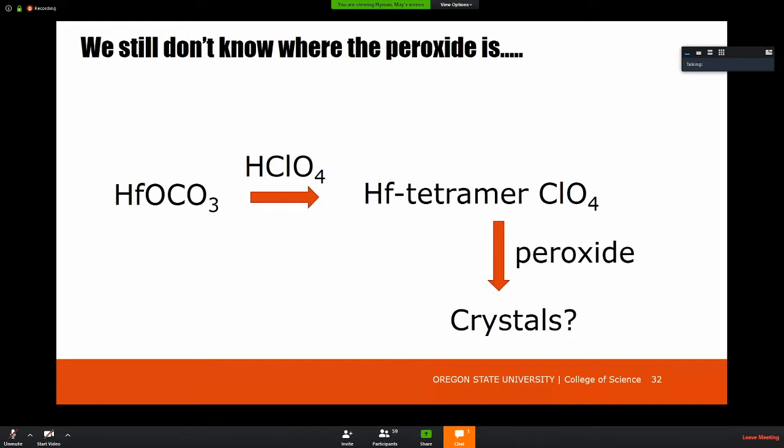Zirconium actually catalyzes decomposition of peroxide and forms oxos. And the oxos link the zirconium into this fluorite-like structure, similar to the UO2 story that you may recall, but in a molecular cluster form. And with time, it breaks up into these tetrahedral clusters that we crystallize out.